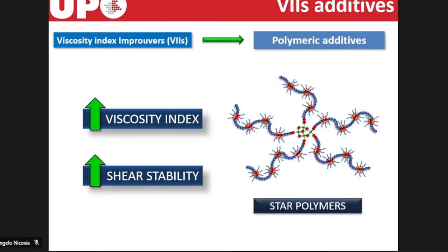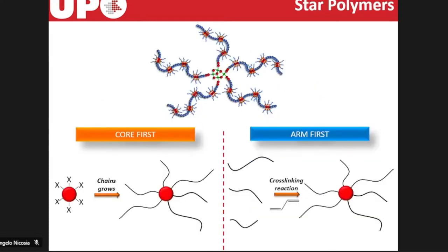We use star copolymers because it is well known that due to their globular structures, they have a greater shear stability than the linear ones. Star copolymers represent a particular macromolecular architecture in which we have linear polymeric arms that are covalently linked to a central core. And there are two main approaches to obtain this type of architecture.